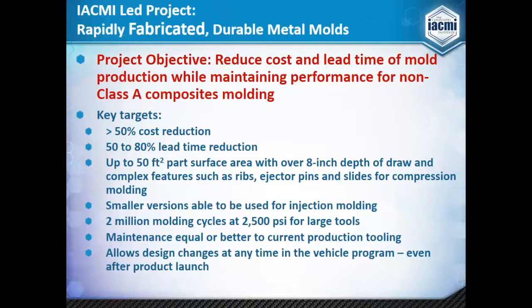We think that within the next couple of years, we want to target getting up to a 50 square foot surface, so something that is 7 feet by 7 feet or larger, so 2 meter by 2 meter part surface with good depth of draw, so not just flat panels, but able to get at least an 8-inch depth of draw that would cover a lot of parts that are out there in the automotive space and in other markets.